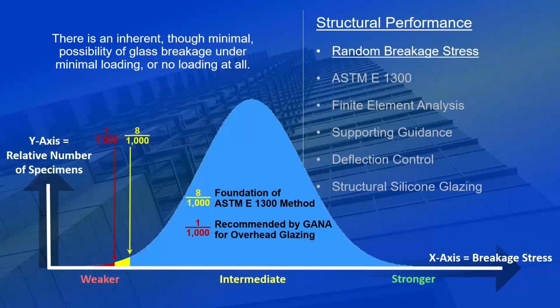1/1000 breakage is recommended by GANA for overhead glazing applications. As a good practice in skylight applications, a laminated inboard light that uses heat-strengthened glass, not tempered glass, is what we often will recommend for most applications because of this breakage concern.